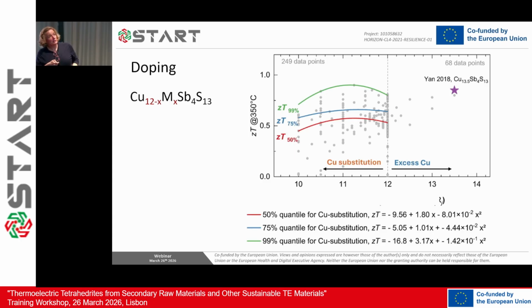These are again the quantiles when you substitute copper—again here it's for all substitutions. We don't have enough data to study individually very well. You see that if you substitute very little, it's good, but if you substitute too much, it's no longer good, in terms of ZT.